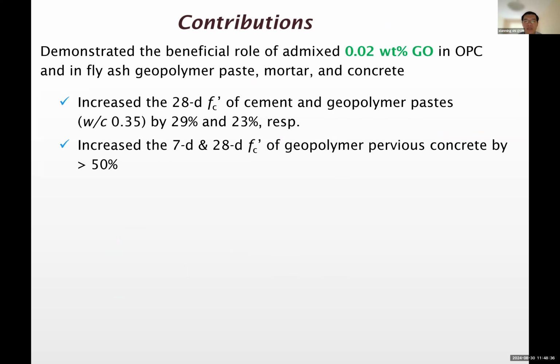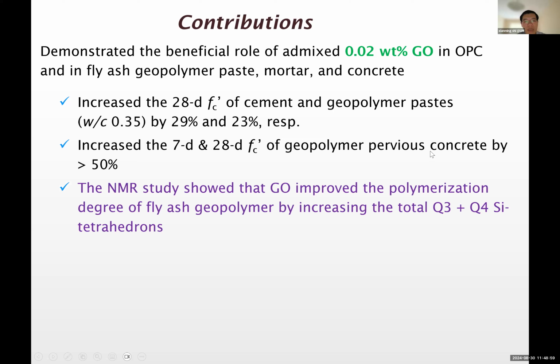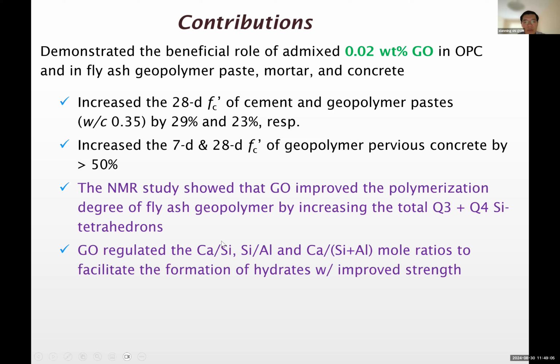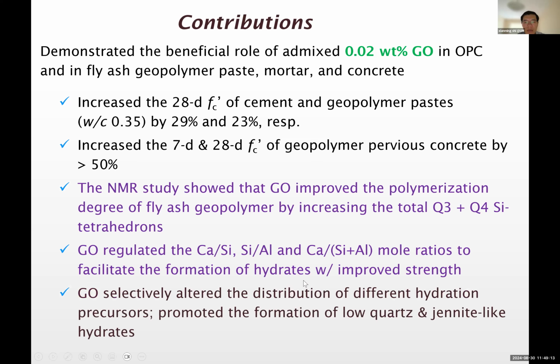So this specific work, basically our contributions are as follows. We demonstrated the beneficial use of mixing 0.02% graphene oxide in OPC and in fly ash geopolymer paste, mortar, and concrete. They increased the compressive strength significantly, and more impressively increased the 7-day and 28-day compressive strength of geopolymer paste and concrete by more than 50%. NMR shows that they improve the polymerization degree, and they also regulate the type of hydration products that would form, and especially favor those with better strength. And there are more mechanisms revealed.